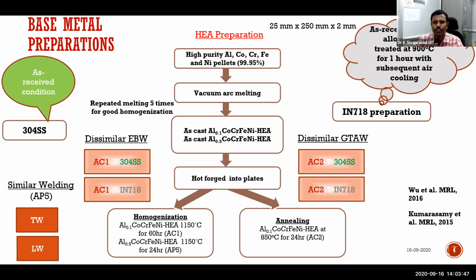And he used to make some 3-4 buttons and remelt them, and then he used to go to the blacksmith, my student. Blacksmithy in a crude way we cannot do, so we have to add a scientific touch there. So he used to do the blacksmithy, and he took an argon cylinder there and purged the surrounding, because otherwise some elements have a tendency to get oxidized, such as chromium and iron, even aluminum. So we don't want elements to get oxidized during hot forging, so he used to do that. Somehow he was able to make small strips of two or three fingers width size.